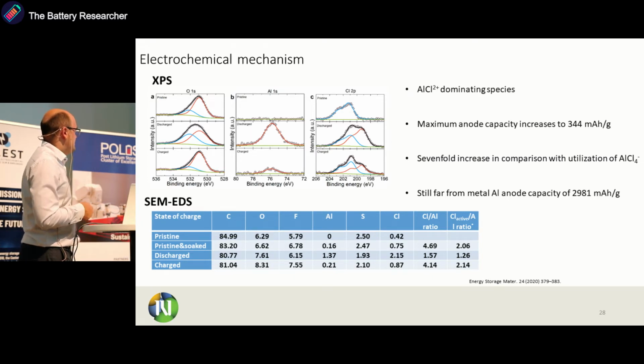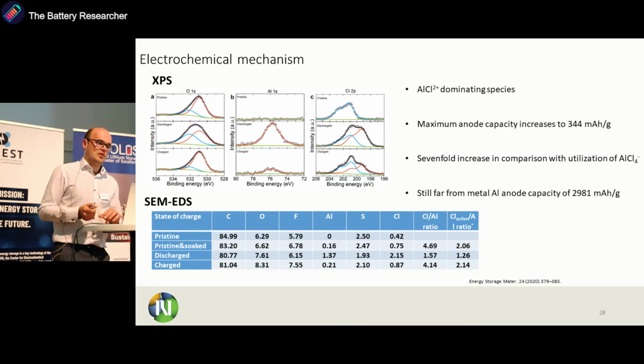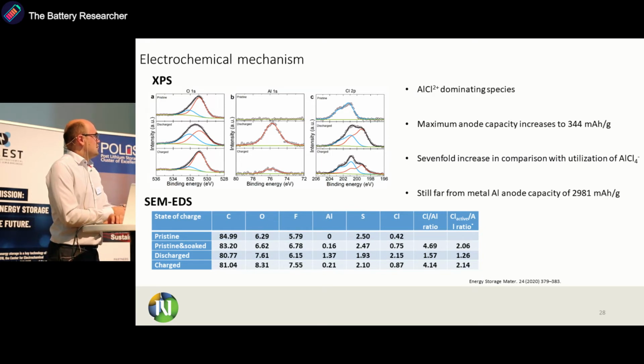We did again SEM-EDS, and this pointed to the ratio between the chloride and aluminum to around 1. So it means that probably we have AlCl2+ as dominating species in our discharged cathode. This means that our maximum anode capacity increases quite a lot from this 50 milliamps per gram to almost 344 milliamps per gram, but actually it's still far from the theoretical capacity of aluminum metal anode, which is almost 3,000.